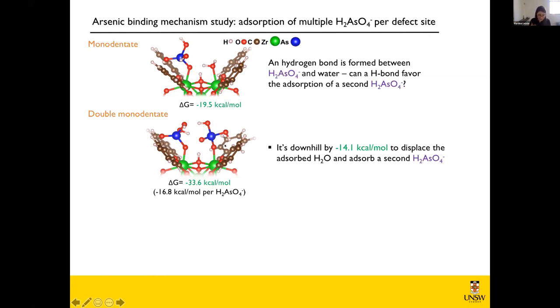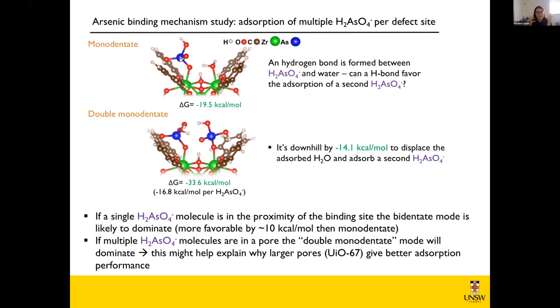If we think a little bit more about the experimental system, I think what we can conclude is that if we are in a condition of low diffusion or small pores, so very few arsenic can be in a pore, then most probably only one arsenic molecule will absorb, and it will absorb in the bidentate fashion, taking over both sides. But if we are in a high diffusion regime with big pores, where more molecules can be in contact with the site, then we might get a kind of double monodentate absorption mode, which again might help explain why the MOFs with bigger pores had a better absorption performance.